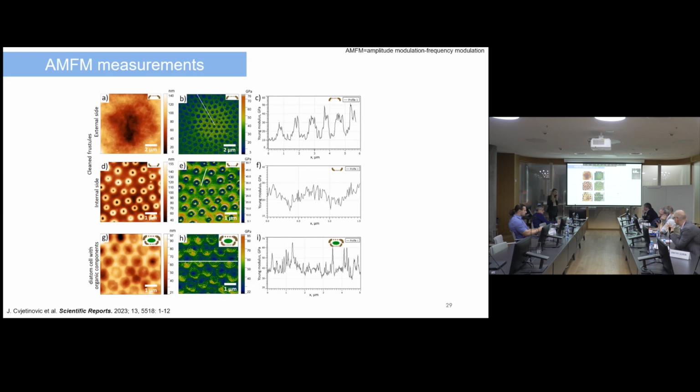It may also include some void parts, which will influence the Young's modulus values. While in this case, we have a volume of a few cubic nanometers. It is only in the surface vicinity. So basically we can say that it does not include any void parts. That is why, in our opinion, we obtained these higher Young's modulus values.